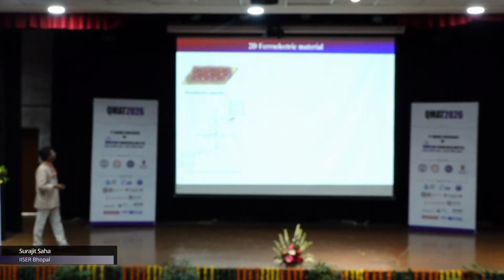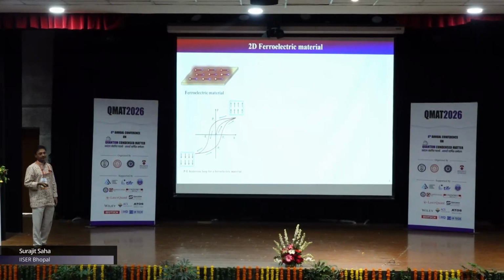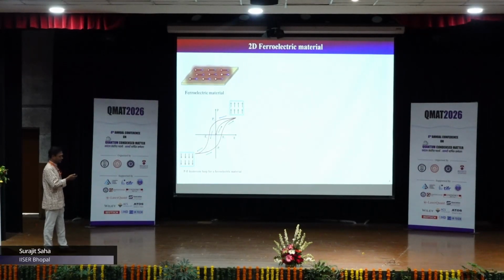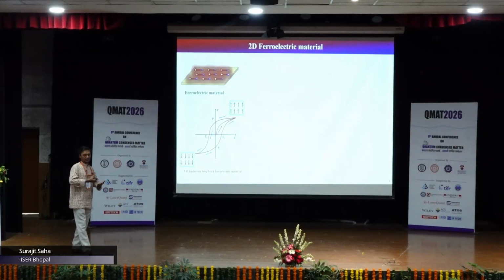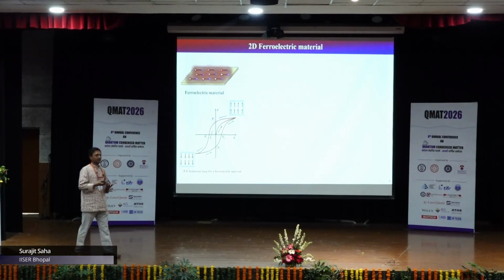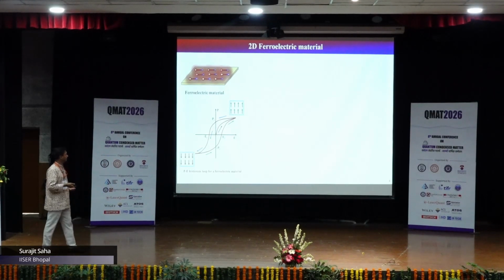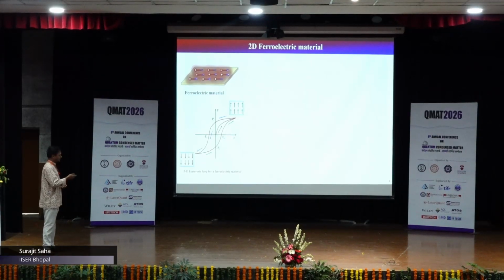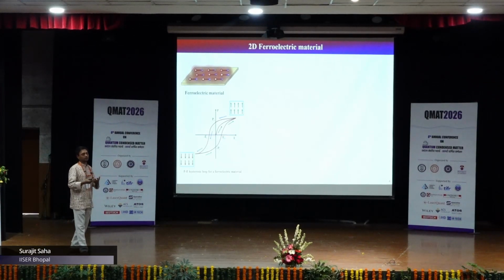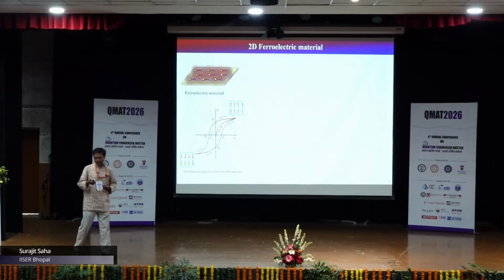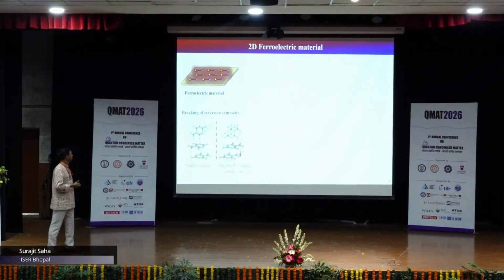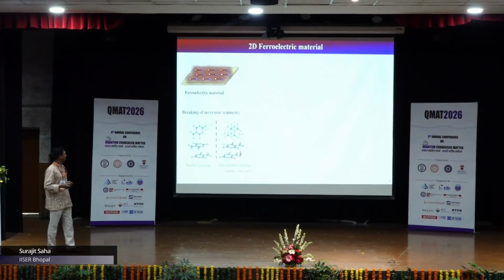All right. So with that, about this indium selenide, which is ferroelectric. When we say ferroelectric, we basically mean that we have these electric dipoles in the individual layers, and of course, this is taken from the 3D picture. And we eventually have a PE loop, which is hysteretic, and the remnant polarization will give us the on and off states accordingly, which can be used for applications.